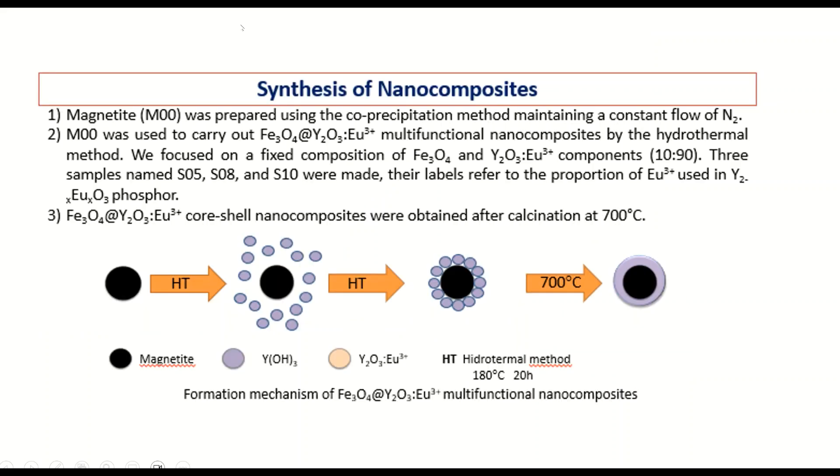For the synthesis of nanocomposites, we first synthesized magnetite. This was using the co-precipitation method. And then, we use the hydrothermal method to obtain the nanocomposites.